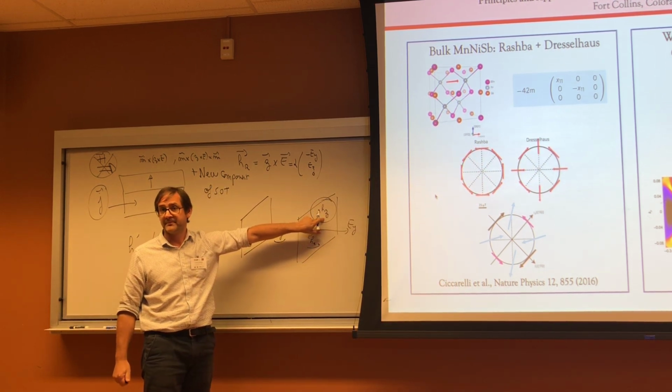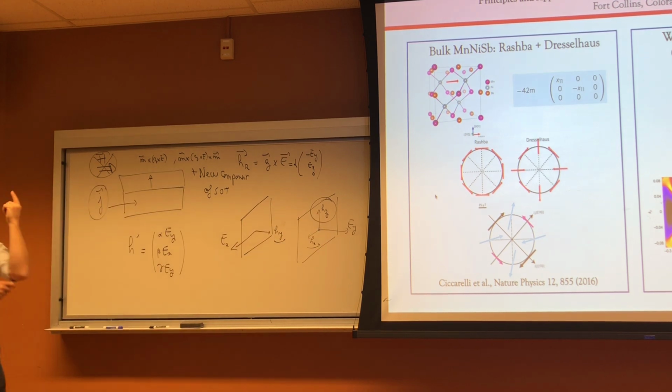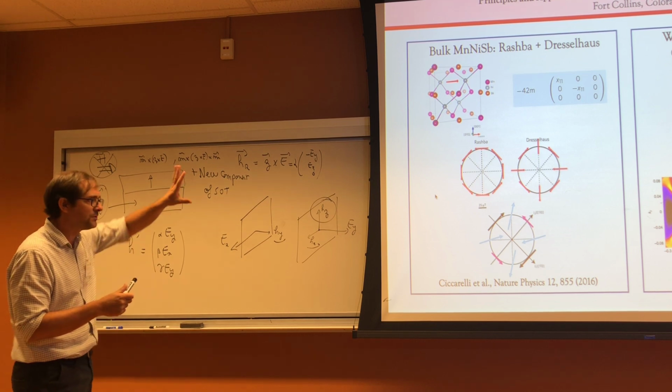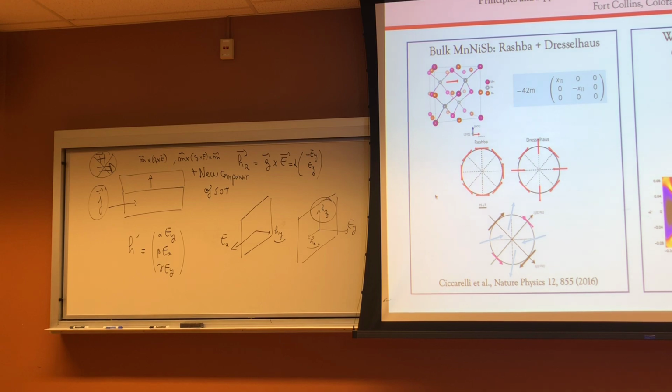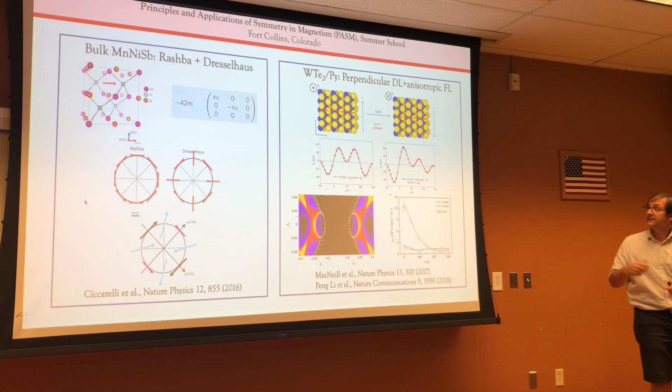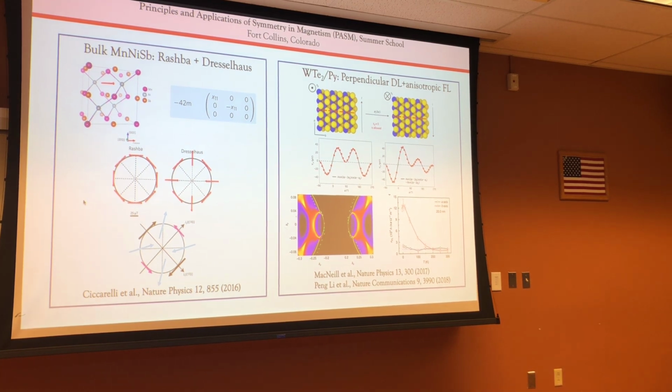the job. Because when you are basically in the plane, then this perpendicular field can complete the magnetization reversal one way or the other. There have been some experiments very recently where I think this has been achieved. It was probably last year, so I didn't show it here. I just wanted to focus on the symmetry. But this is to tell you that the crystal symmetry of the system that you are working with can be very useful and can be engineered to complete the magnetization and to have some field-free switching.